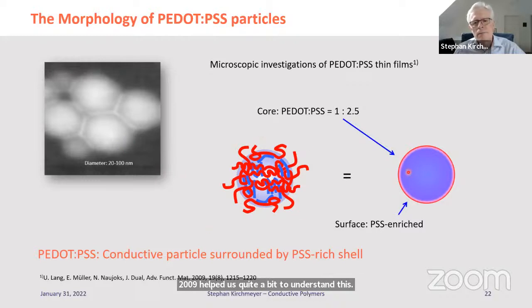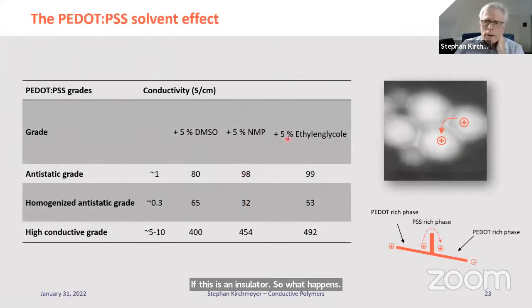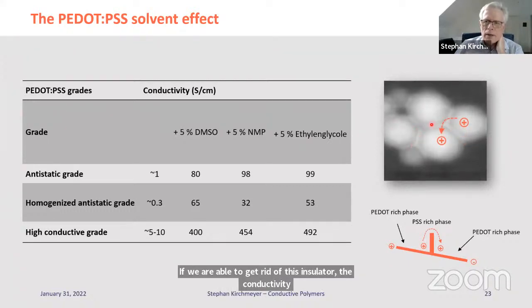So the PEDOT itself has PSS strands, which are somehow connected to the PEDOT strands. They look like these, and we can understand them as a particle which has PSS on the outside, enriched PSS, and enriched PEDOT on the inside. This works like an insulator. If this is an insulator, so what happens? Very simple. If we are able to get rid of this insulator, the conductivity will become much higher than if we remain with this.